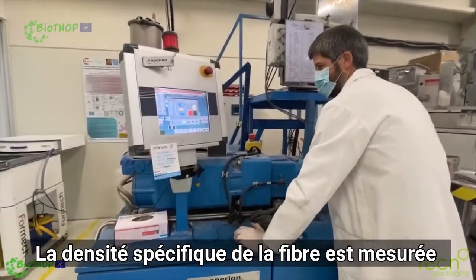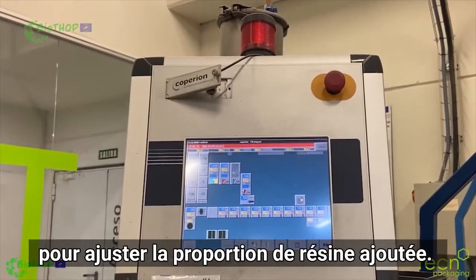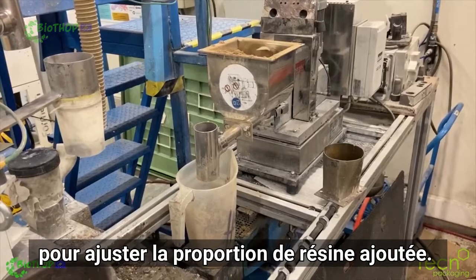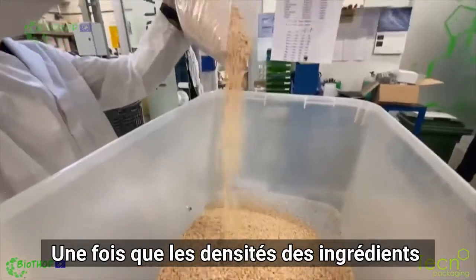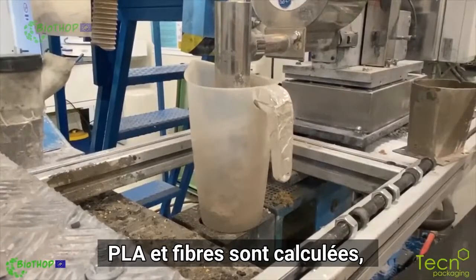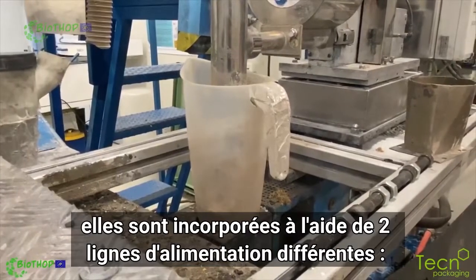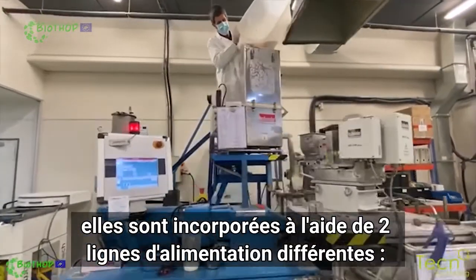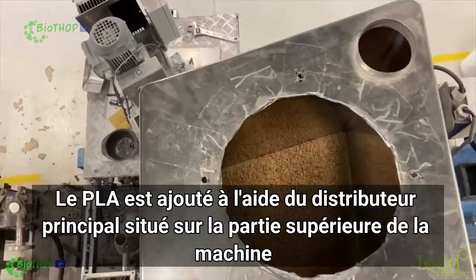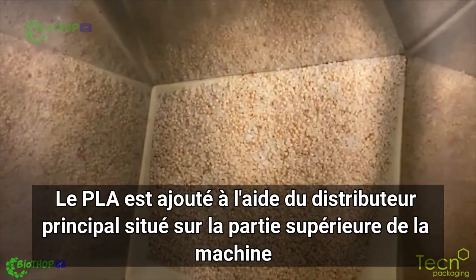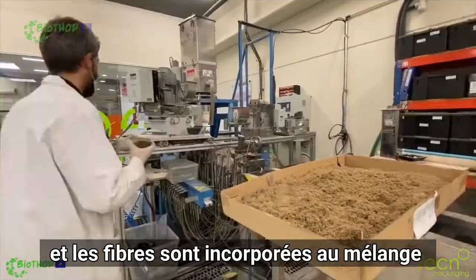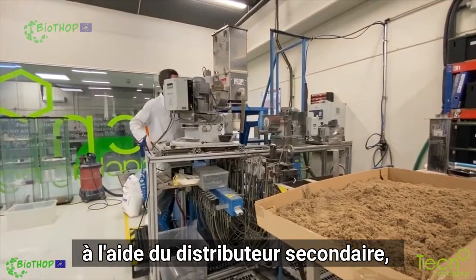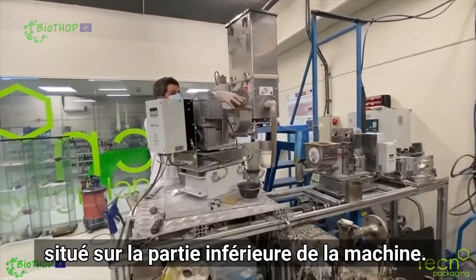The specific density of the fiber is calculated to control the percentage dosage added to the compound. Once the densities of the ingredients, PLA and fibers, are calculated, they are incorporated using two different feeders. PLA is added using the main feeder on the top side of the machine, and the fibers are incorporated into the blend using the secondary feeder located on the lower part of the machine.